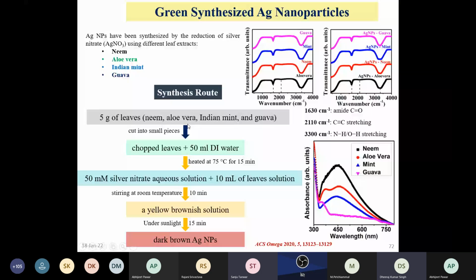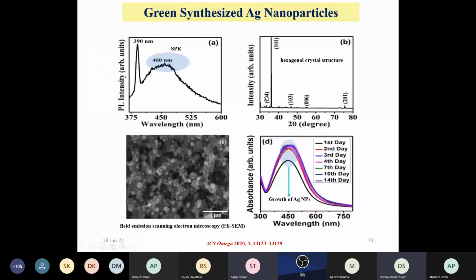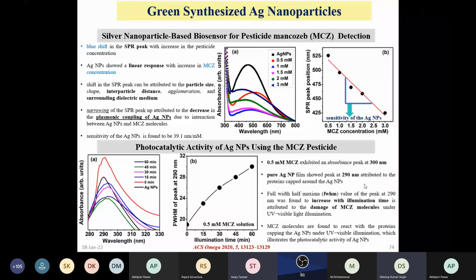So means a lot of types of silver, and further you can do XRD, like hexagonal crystal structure obtained by this peak in XRD. Surface plasmon resonance can be seen by UV, and after several days you can see that your silver nanoparticle are still stabilized in the presence of a particular ligand. So green synthesis of silver nanoparticle and photocatalytic activity of silver nanoparticle using various plants was given. A lot of papers are also published.